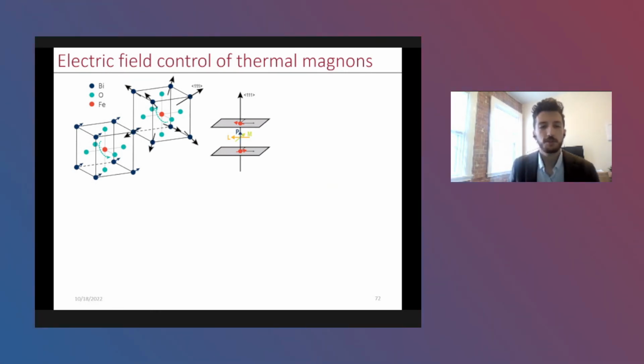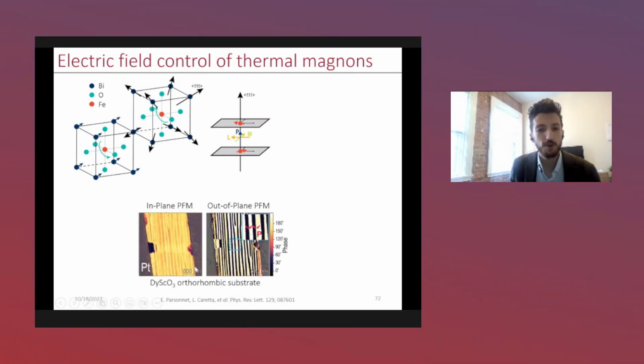The challenge with bismuth ferrite is that in its bulk phase, all orientations of the polarization along each cubic diagonal direction are degenerate. So these are all equally likely to form, which means that the magnetic orientation also has 8 degenerate orientations. Luckily, we can use epitaxy, or atomically precise synthesis, and use strain from symmetry-breaking substrates like orthorhombic substrates to isolate 2 of these vectors. So instead of having all 8, we can stabilize just 2, which are across a base diagonal that you can see here.